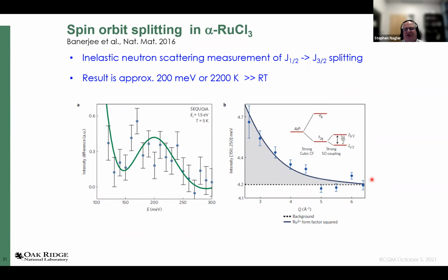So if one is at temperatures low compared to that, then effectively each of these ruthenium 3+ behaves as a J effective equals a half system, or even if there are other perturbations, it's doubly degenerate and it's mixed spin orbital, which, as we'll see, can be good enough.